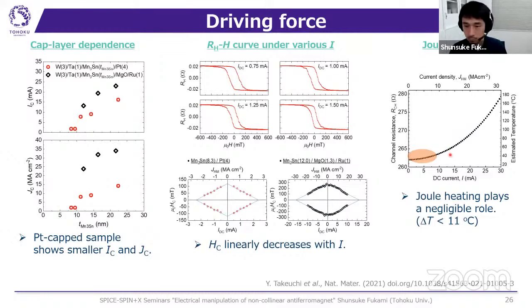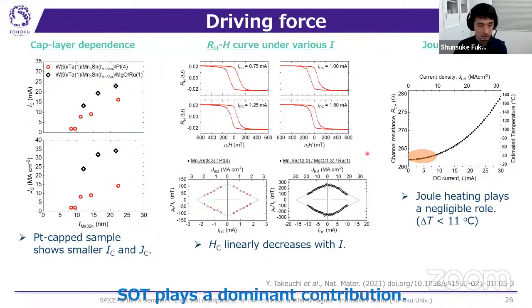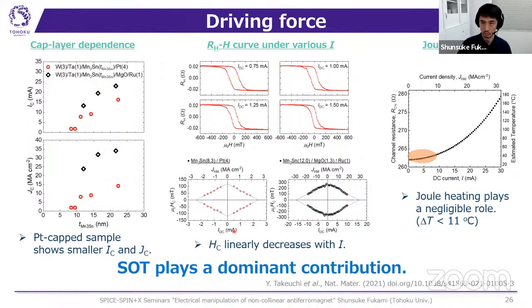And finally, we also evaluate the Joule heating. We first measured the channel resistance as a function of the temperature. After that, we measured the channel resistance as a function of the DC current, and the result is shown here. At a current below 10 milliamps, the temperature increase is less than around 10 degrees Celsius. So we can say that the Joule heating plays a negligible role. These results suggest that the spin orbit torque plays the dominant contribution.